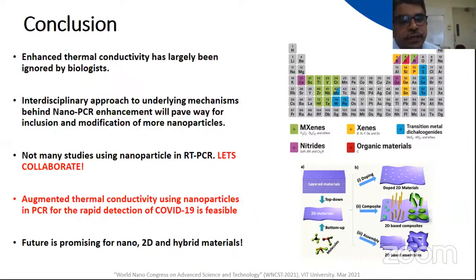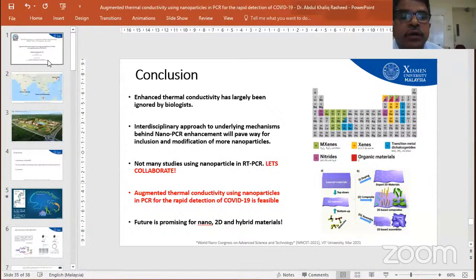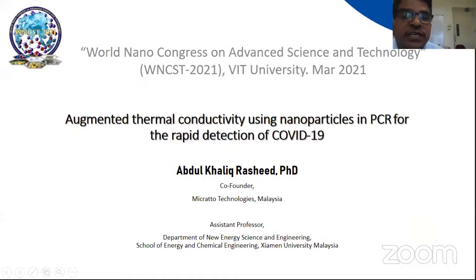Yeah, it's very nice. It will be very important because in a clinical setting, the robustness with which we handle the number of samples per day per productive time is going to matter a lot. And also, if you reduce the number of cycles, instead of doing 35 or 40 cycles, if you do 20 or 25 cycles, it will also reduce the cost of the materials. For instance, the fluorescent probes are extremely expensive. You can cut down the cost of the PCR analysis. Instead of paying 2,000 rupees per test, if one can get it done at 1,000 or 1,200 rupees, it's a lot of cost saving, I would say.